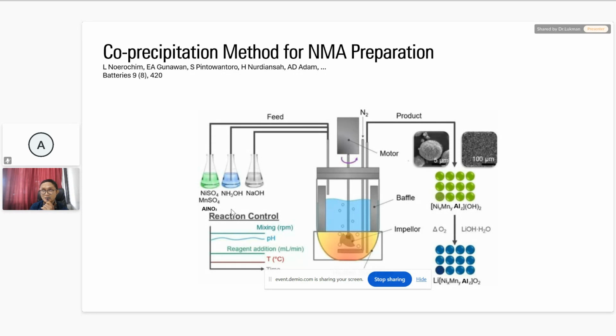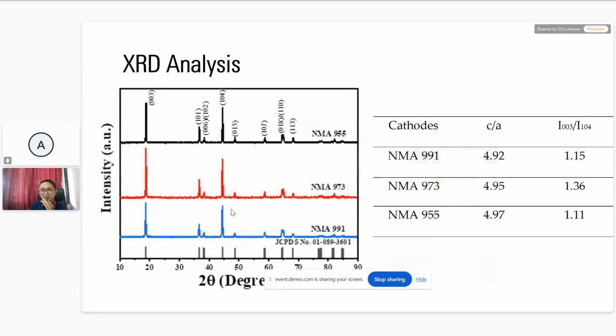And I suggest you make sure to control the flow rate of the gas, yeah, because it will affect the smoothness of the surface of the particle. Okay, after that is finished, we will call the as-prepared material NMA. For this preparation, we make three variations of the aluminum concentration. I can show you later. The three variations here are NMA 991, NMA 973, and NMA 955.